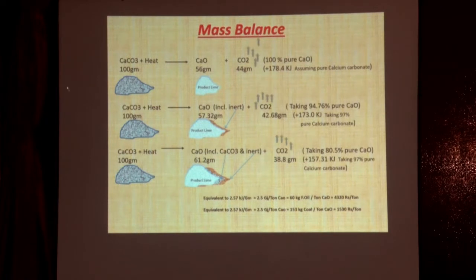And the third one, usually if you see, normally people don't produce lime purity as high as 90. If you observe the data across the industry, they are stable at the purity of 80 to 85%. If you are producing 80.5% purity, the fuel requirement will be 157.31 kilojoule for 100 gram.